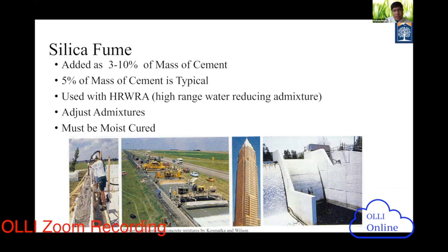It was already mentioned that 3 to 10% of the mass of the cement is generally used as silica fume. 5% is very common, and it is used with high range water reducing admixture. So cost will increase, and it must be moist cured properly. You see all the construction with the different materials that we talked about so far. Fly ash, we talked about buildings, silica fume is very common. In the dam, as you see, we are heavily using slag, and some fast paving construction can also use silica fume.